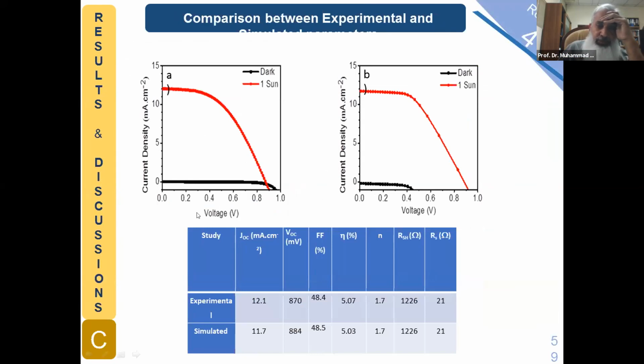Now, we have also done simulation of that, and using a semi-empirical approach, by using the actual values of series and shunt resistance, we were able to simulate results in very good agreement with the measured ones. You can see that the simulated and experimental results are in very good agreement if the actual values of series and shunt resistance are included, and then other values are optimized, like the thickness of the films and the band gap of the perovskite.